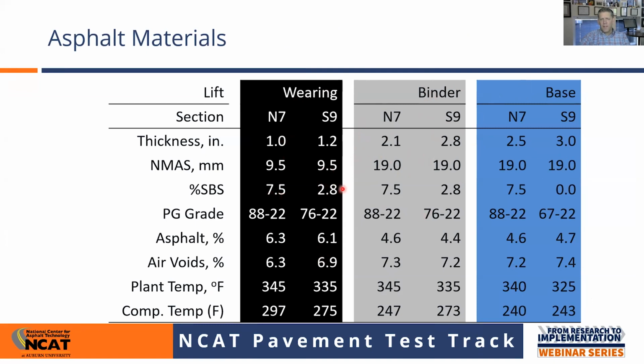The polymer loading, as I said, in the wearing and binder courses, we did have SBS polymer in the control, 7.5% in the Kraton. No polymer in the base mix for the control section. You can see how it grades out here. The volumetrics were fairly comparable between the two. The plant temperature, we ran it a bit higher, I think on the recommendation of Kraton, to run the plant a bit hotter when working with that material. And then you can see here the compaction temperature.